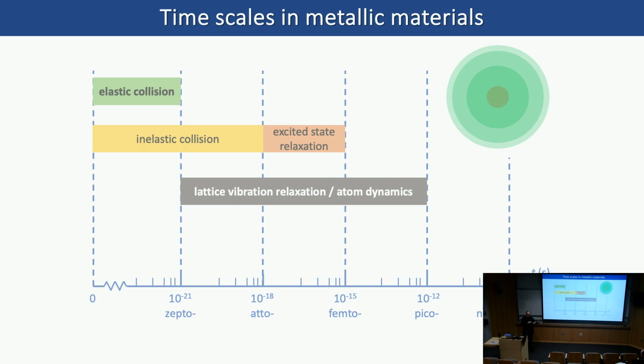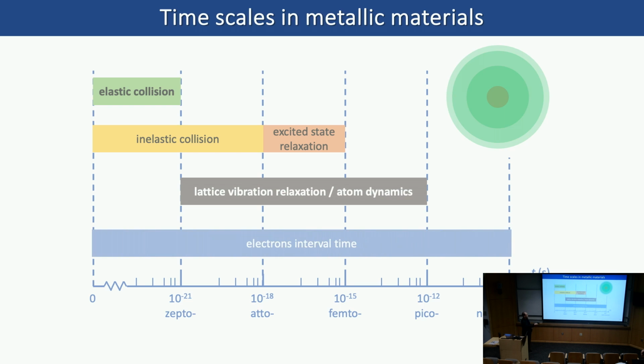Once you have this elastic collision, your lattice is going to vibrate. So it takes about picosecond on the time scale for the lattice vibration to relax back to a near ground state. So that's also the phonon lifetime. It's on the range of this order. For the brightest electron source you could possibly get, which is a cold field emission source, the electron interval time, so that's marking the time interval between the two electrons hitting the atom one at a time, is on the order of nanosecond. So even with the brightest electron source, you still get nanosecond time interval. So what you can see is these time scales are very well separated from each other. So when you see that, if I want to simulate any of those, I could basically consider one, while considering the other to be not happening or has already happened and fully relaxed. So that's a good thing for us.